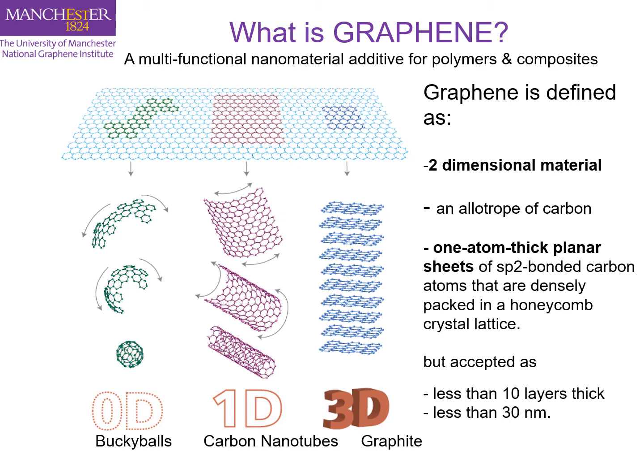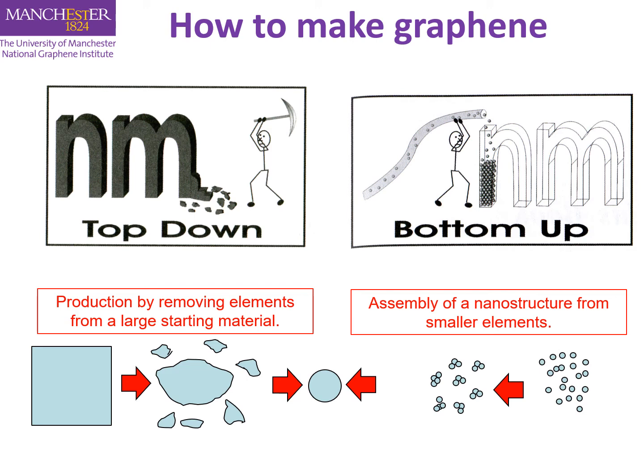Graphene is defined as a two-dimensional material, an allotrope of carbon, that can be used as an additive for polymers and composites. And it is accepted as graphene provided that the platelet is less than 10 layers thick and less than 30 nanometers in thickness. We can produce graphene by removing elements from a large starting material like graphite, or we can assemble a nanostructure from smaller elements, so we can build the material atom by atom.